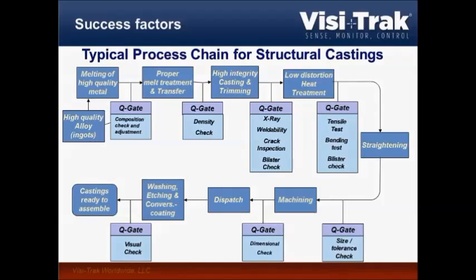High quality alloys, we move that to the back. We'll come back to this later on. We'll start off with melting and melt treatment, and typically then we do a composition check and adjustment, proper melt treatment and transfer, do a density check, then the high integrity casting and trimming itself. After that, depending on the requirements, you might see X-ray weldability, crack inspection, and then I say here low distortion heat treatment, because these very large surface, thin-walled, dangly parts, they distort pretty well when you put them into a typical water quench. So you have to work with precision air quench when you come out of the solution heat treatment. After that, you have your properties.